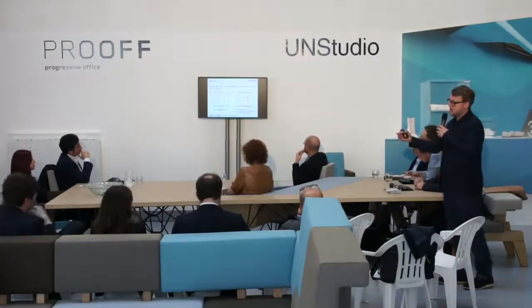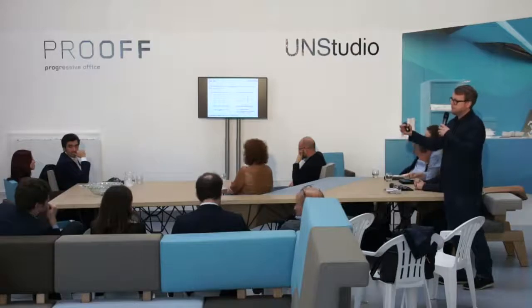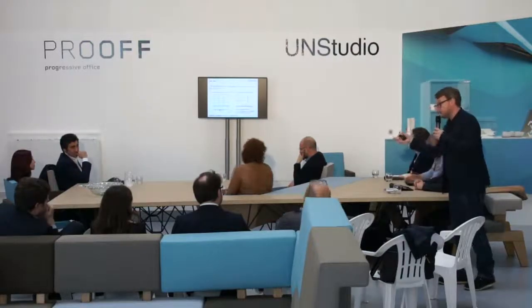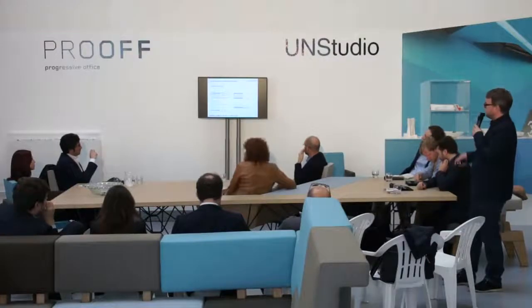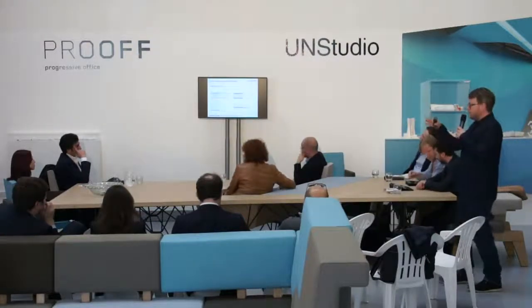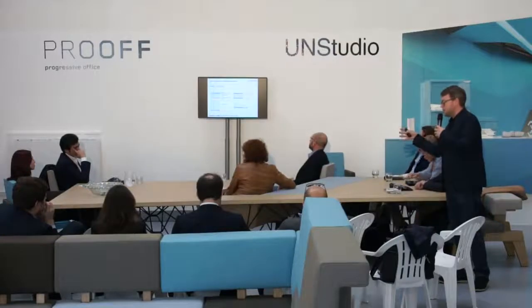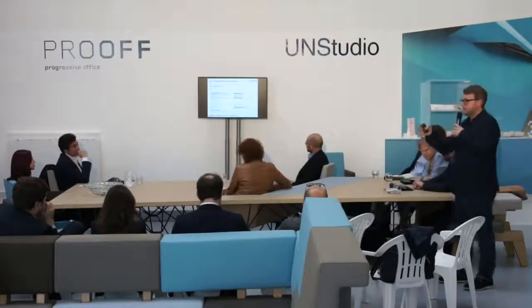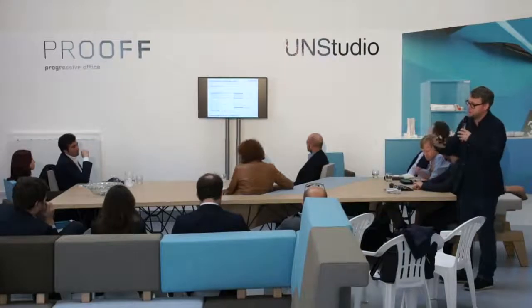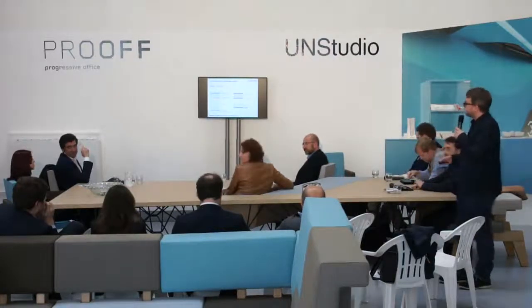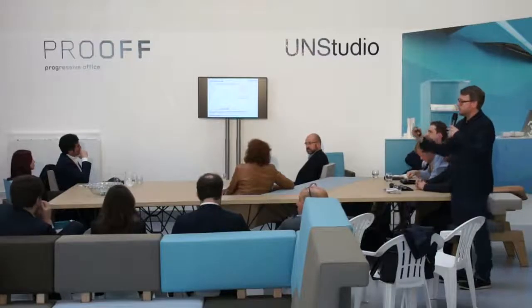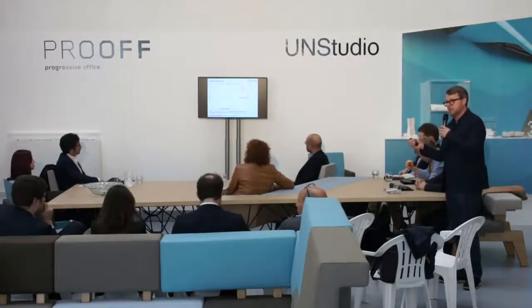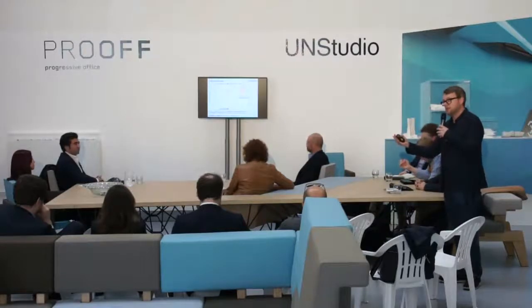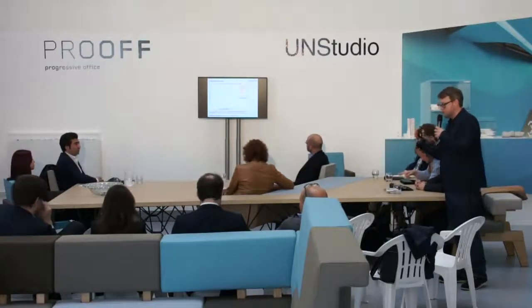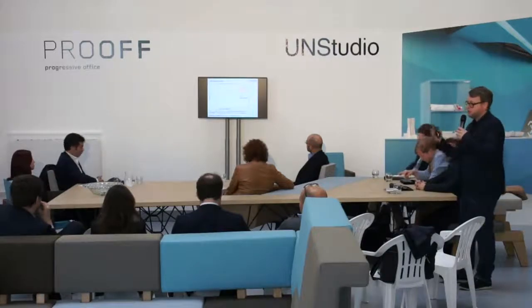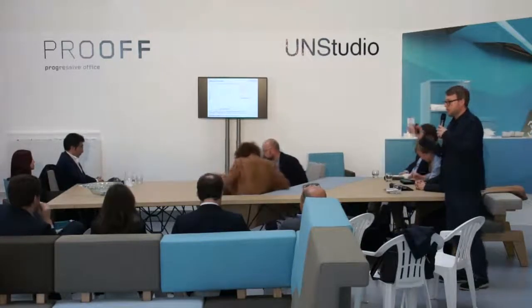Well, it tends to be in something that needs to perform in a very unique action, like a bomb or a security issue like that. So we're starting to head down the road of things that need this particular post-breakage strength, and also things that might need this light touch, light materials, lightweight glass, as I like to call it. For all intents and purposes, you're looking at it and feeling a piece of glass, but in fact its central body is that of an acrylic. You get away from the greenness that's in the glass because the acrylic is completely clear. So you can have a 15, 20 millimeter piece of glass that has no greenness to it whatsoever.